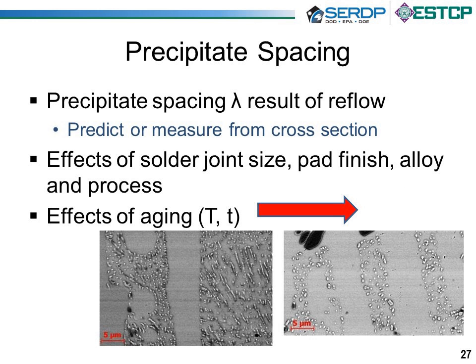Now, the precipitate spacing is originally determined by how we form the solder joints. In realistic manufacturing, where you solder anything, you melt the solder, put it in contact with the metal contact pads that you want to bond to, and then you cool down the solder so it solidifies, and you have a solder joint. And you do the same thing in manufacturing, and realistically what happens is that there is a variability in that process. And that's a fundamental variability, nothing you can do about it really.